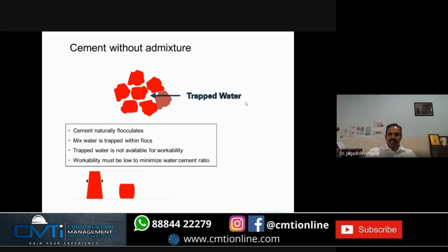I'll just give you the concept of what chemical admixture, particularly plasticizer, does. When you add water to the cement, cement naturally flocculates. Flocculates in the sense all the particles come together. It forms a lump kind of thing. So in these lumps or flocks, mixed water gets trapped within the flock. If you burst the flock, the water inside will come out. So this trapped water generally is not available for workability, so you have to add some kind of admixture to release this trapped water so that workability will increase.